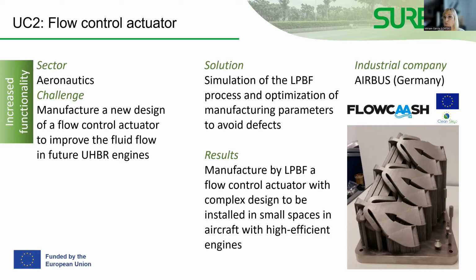We also optimize the manufacturing parameters to avoid defects, and we obtain this prototype that you are seeing here in the picture, which is a flow control actuator with a very, very complex design. Actually, we had to face many problems. For example, the powder was stuck inside the internal channels. So we had to be very imaginative in order to create solutions to take out this powder before making the thermal treatments of the parts, in order to have full functionality of the parts. Actually, Airbus was very happy with the results.